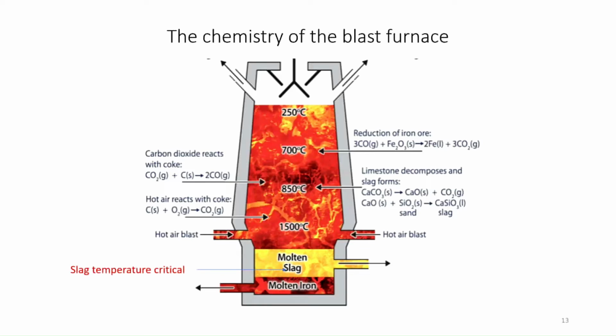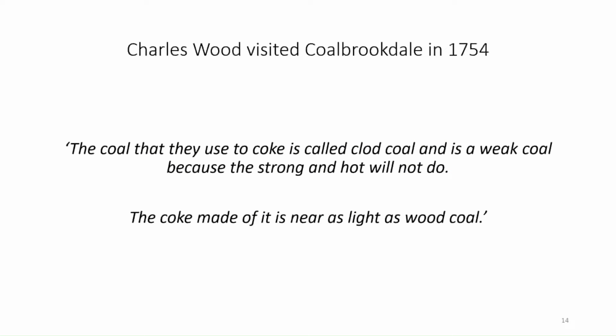What that meant was also that even if you had a reactive coke, you had to be very careful to make sure that you didn't push the temperature of the hearth too high, because you would do the same thing. If you had too hot a hearth, you would again push the reduction zone out of the top of the furnace, which meant that you were limited in how hot you could have your hearth. Now, you will read lots and lots of reports that have been made prior to me coming along, where they would tell you that the coke-fired blast furnace was hotter than the charcoal one. It wasn't, not in the hearth anyway. In fact, it had to keep the hearth quite low in temperature, simply to make sure that it got the reduction zone in the right place. But this is a little bit just to prove the point. This is the coal coke that they used in the Coalbrookdale furnace, the Dale Company furnace, was nearly as light as wood coal.